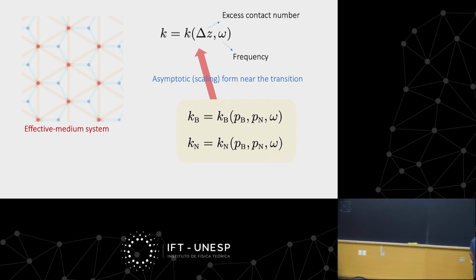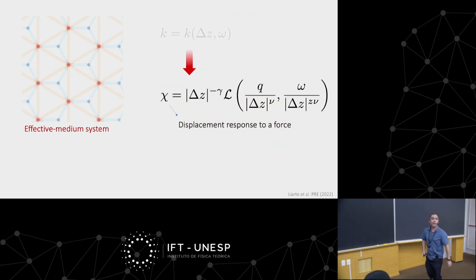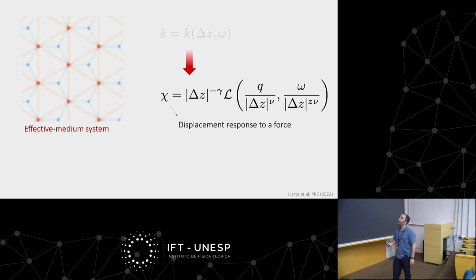So you get something like this, and from this, you can calculate something like a susceptibility, a generalized susceptibility. This is a displacement response to a force. This is a general scaling form for this susceptibility. I do not have time to go into the details of this, but there is a power law here and a universal scaling function here in terms of wave vector, rescaled wave vector, and frequency, in this case. And gamma, nu, and z are critical exponents. And this curly L here is supposedly a universal scaling function.